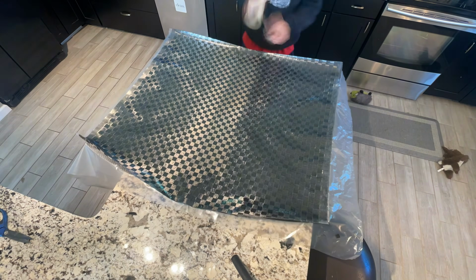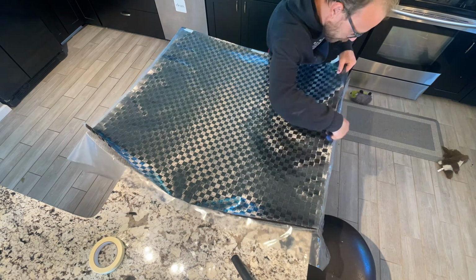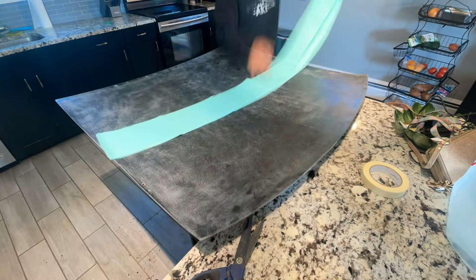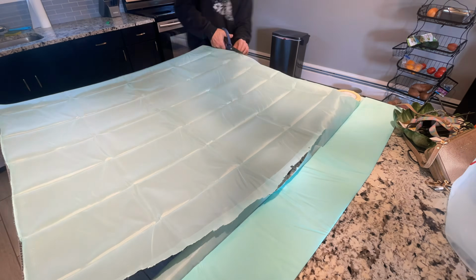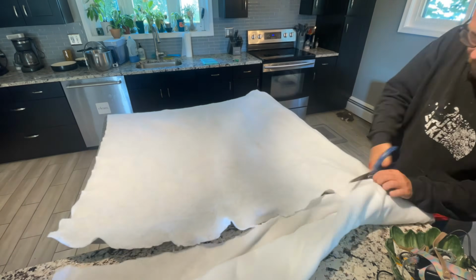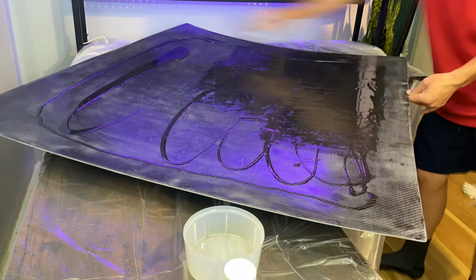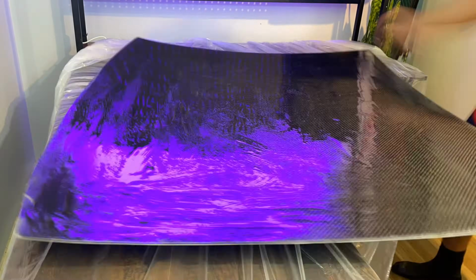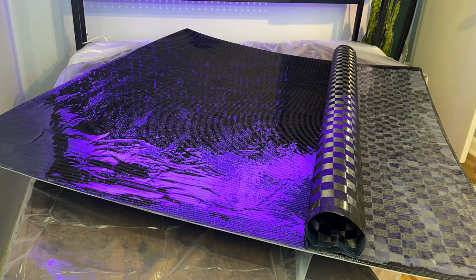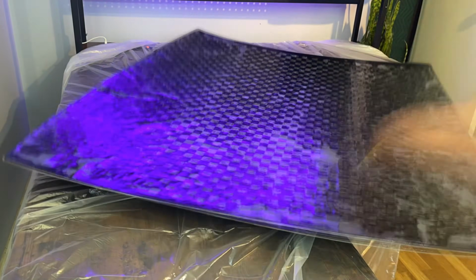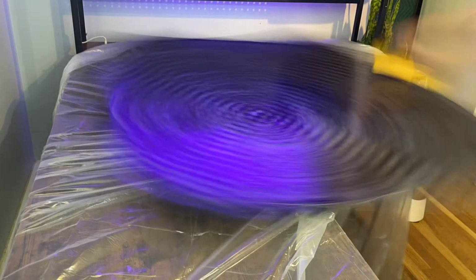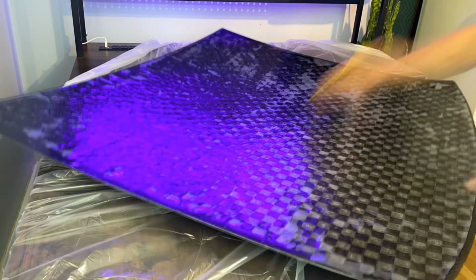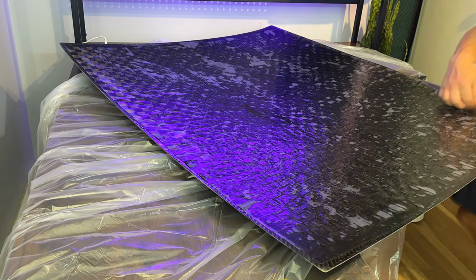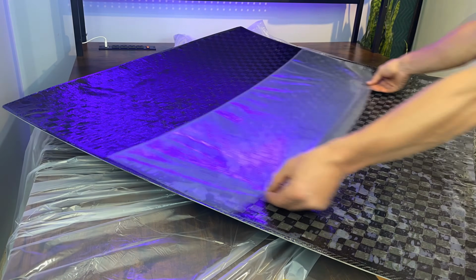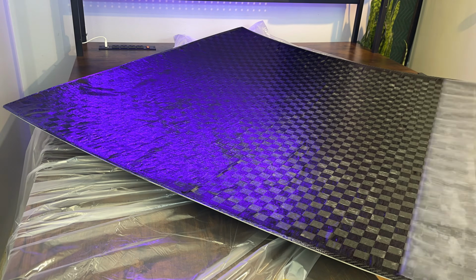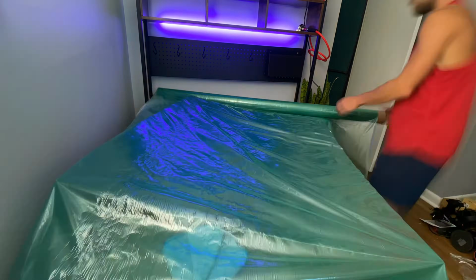I began the process by getting all my materials cut to size. You want your bag, peel ply, and breather material to be slightly larger than your carbon fiber panel. Once all the layers were ready, I mixed up a batch of epoxy and applied a thick, uniform layer using a brush. Next, I carefully laid the carbon fabric, plastic backing side up, on the epoxy and smoothed out all the air using a roller and a plastic spreader. Once the carbon was firmly adhered to the fabric and fully saturated with epoxy, I removed the plastic backing and inserted it into the vacuum bag I made using the gasket tape.